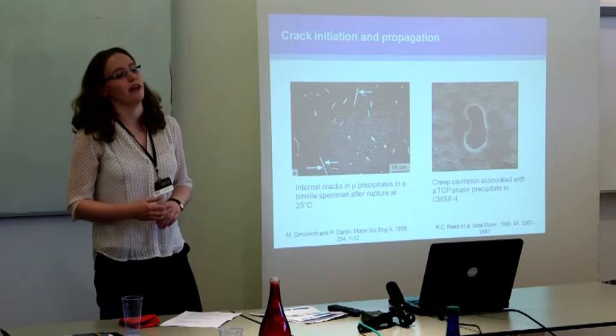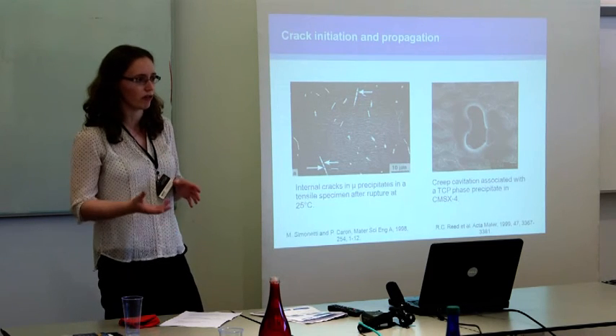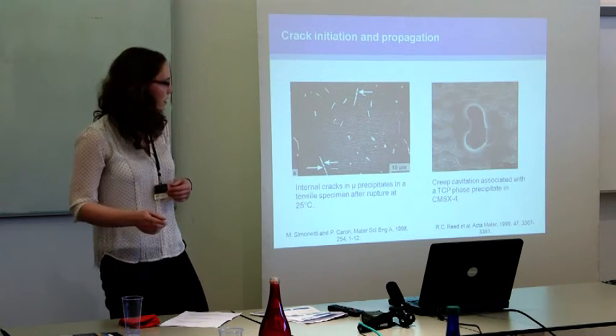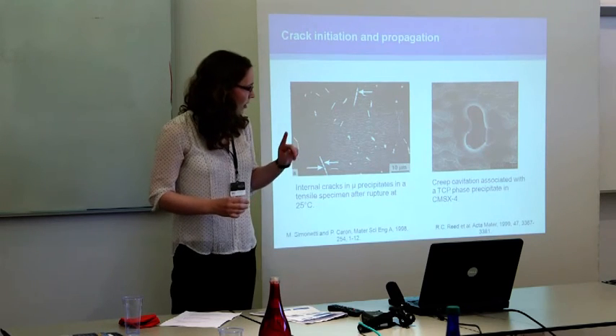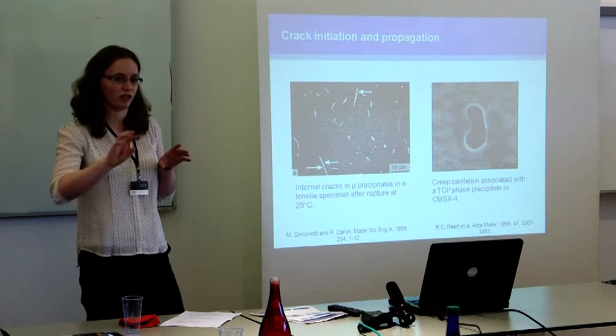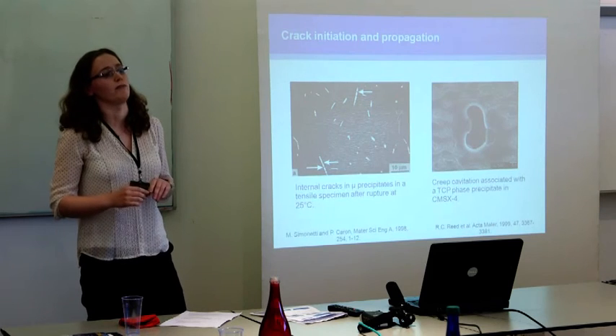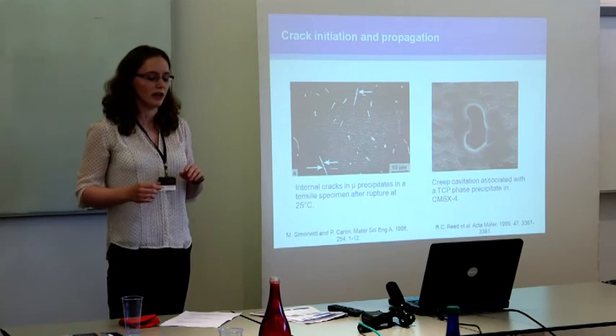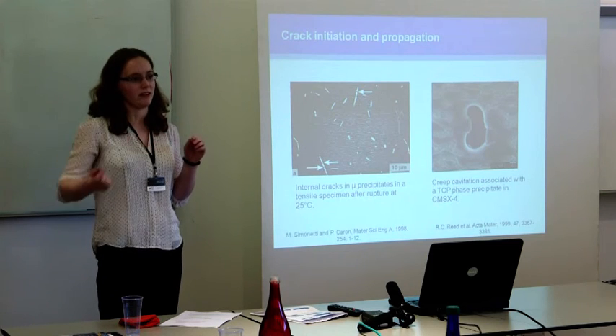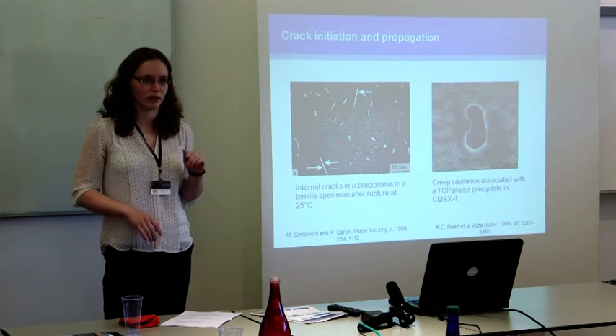Other mechanisms by which TCPs can affect crack initiation involve pores. Particularly when TCP phases form at high temperatures, they are often associated with the formation of cavities near them, which can then act as crack initiation sites. An example here is creep cavitation, where cavities formed during tertiary creep provided initiation sites at TCPs for failure to occur. A final related mechanism is that TCP phases can form as continuous brittle phases along grain boundaries, providing very easy crack propagation paths and greatly reducing various mechanical properties.